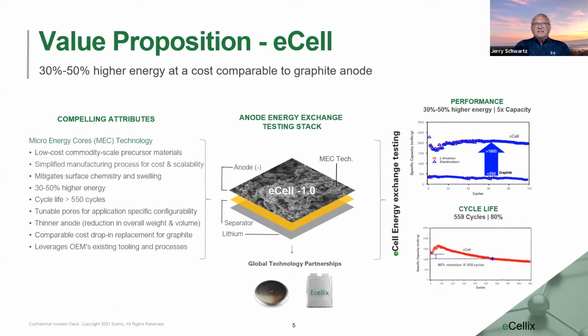The thing about silicon is that it has 10x the electrochemical capacity of graphite. So there's a lot of capacity there if you can make it work. We're finding that our material tops out right now at about 7x, which is 2,500 milliamp hours per gram, compared to 372 for graphite. So there's a tremendous opportunity in making that evolution. Keep in mind that lithium-ion batteries for the last 30 years have improved in capacity about 1.5 to 2% per year based upon process improvement and some other aspects of it, but no monumental, quantum changes. This would reflect somewhere in the neighborhood of a 50% improvement.